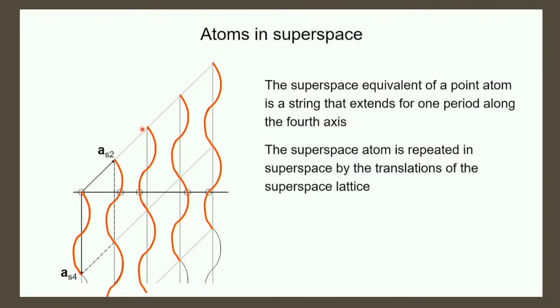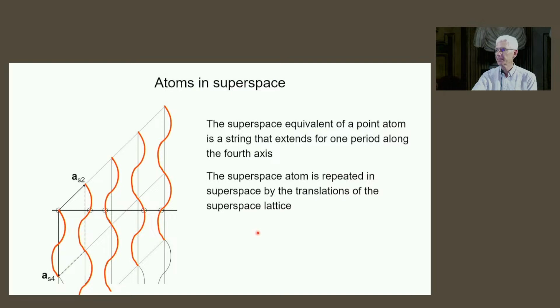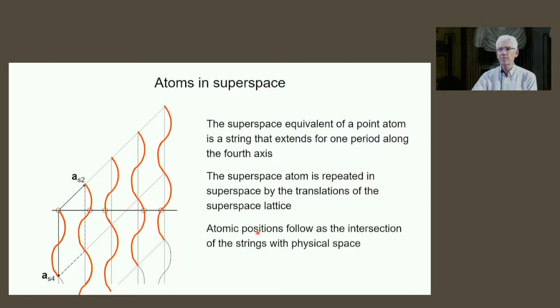We go up with the second superspace translation, we get all these strings, and then we go down with AS4, and then we fill up all of space with atoms, and now we see that an atomic string extends infinitely long and is periodic along the fourth axis. And the atomic positions, very important, now follow as the intersection of the wavy string with physical space. So that are all these real modulated positions you find here.